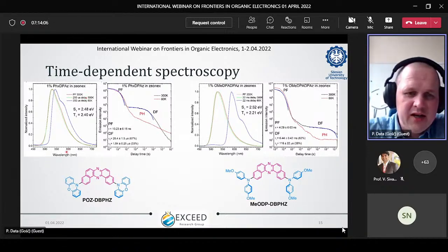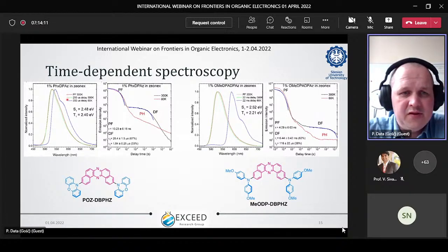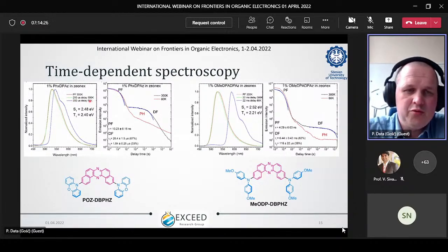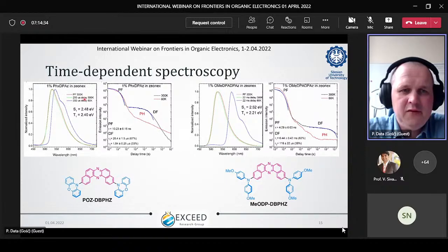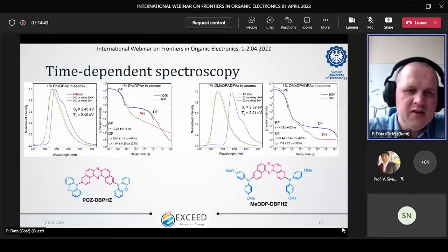In the case of this compound, which I showed here, you can see that our blue curve, blue spectra, is the phosphorescence, is the delayed emission at 80 kelvins, which means we froze our molecules to avoid that they will move, and we would see some delayed emission or reverse intersystem process. If we would heat up our molecule, we have our prompt fluorescence, so very fast nanosecond fluorescence, which is here. You see the red curve, red spectra.